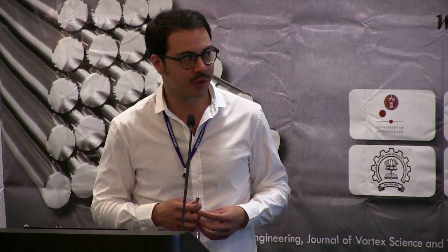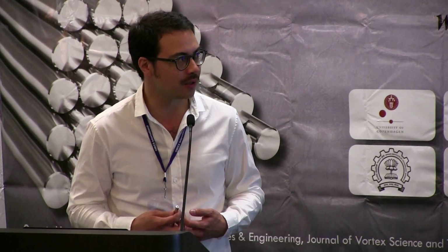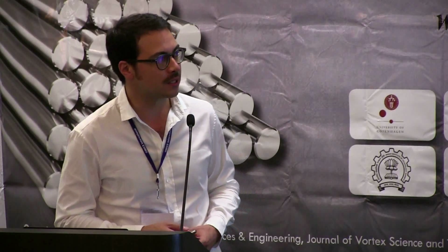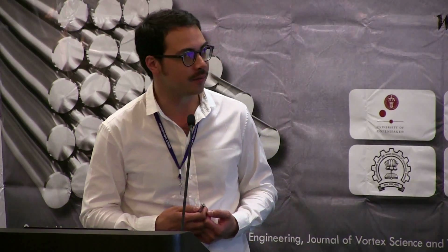So basically, this is the laser pointer. Okay, so we don't regard the process of the manufacturing of the ingot. So we start with the wire drawing, and after a degree of deformation of up to 40%, there's normally an intermediate annealing, up to 800 degrees Celsius, to make the material deformable again. And then you repeat this process until you have the required diameter of the wire. And as a last step, you have the final heat treatment.